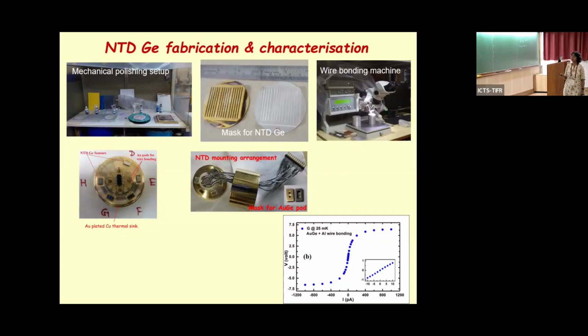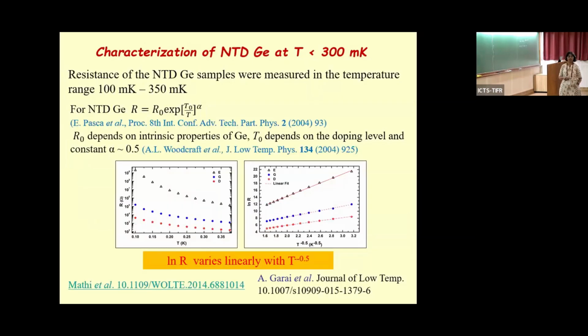The first thing you do with a sensor is check the VI characteristics, because having good linear VI characteristics at low temperature is state of the art. It doesn't happen on every piece you make. There's a lot of rejection. Then you also work out your bonding and contact making procedures based on that. This is why you see a blown up area close to the origin. So, okay, good. We have a good sensor at least.